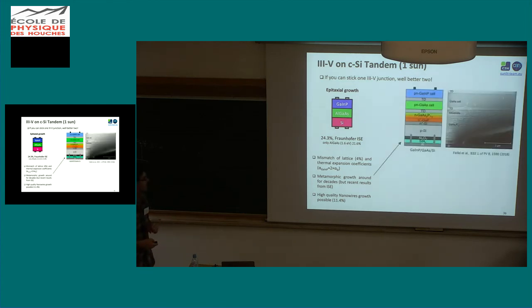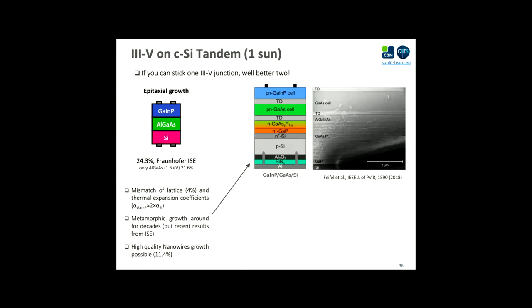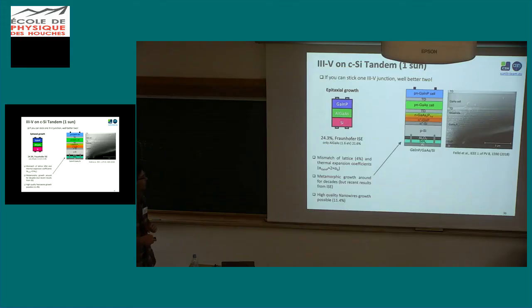But nevertheless, there have also been recent results from Fraunhofer, I believe last year, 24.3% with this configuration, gallium indium phosphide, gallium arsenide and silicon. And this is what I was mentioning before, this metamorphic growth. The idea is that you start with this silicon bottom cell and you start to grow some gallium phosphide. Gallium phosphide is more or less lattice matched with silicon, and then you start to slightly change the stoichiometry of gallium phosphide through gallium arsenide phosphide until you get to gallium arsenide.